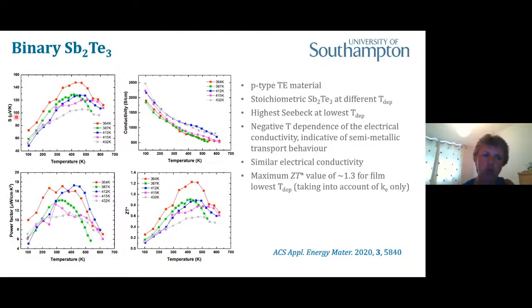So this is looking at the Seebeck coefficient as a function of temperature here, and you can see very clearly where these materials have their maximum. And this is showing that as we deposit these materials at different temperatures, we see quite a variation in the Seebeck coefficient, which is going to be important in tuning and optimizing the thermoelectric generators that we're producing. Indeed, these are P-type semiconductors, and that's clear from the data. And if we work this through, we can anticipate a maximum ZT value of about 1.3 for the film undertaken at the lowest deposition temperature.